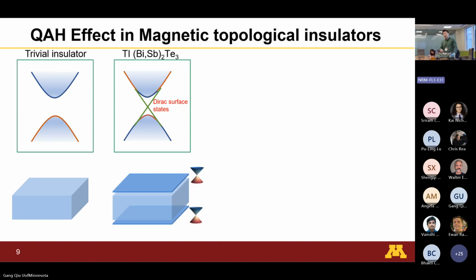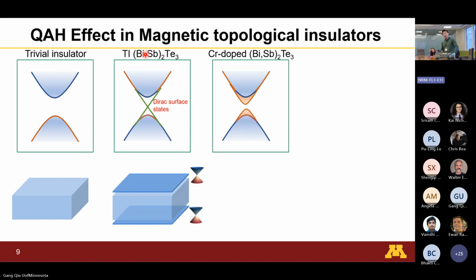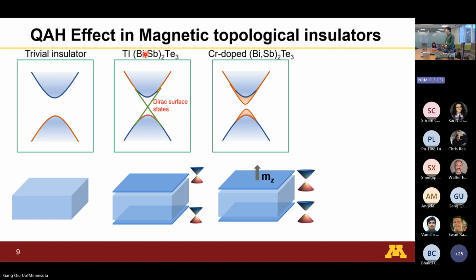Of course, I draw it this way to highlight that metallic surface. It's not detached from the film. It's still on the material, and of course there will be some side walls for now. In this case, bismuth antimony telluride is one of these topological insulators. Now we want to introduce magnetism. We add some chromium. Chromium gives a perpendicular magnetic anisotropy to BST. So what happens is this magnetization introduces a Zeeman gap on the surface states. This cracks open the Dirac surface states.